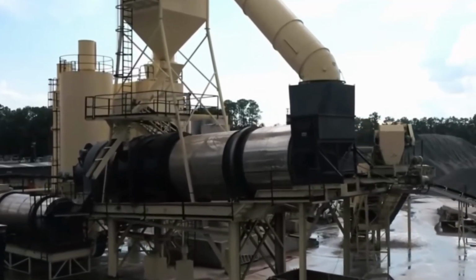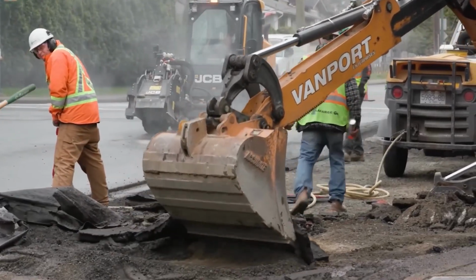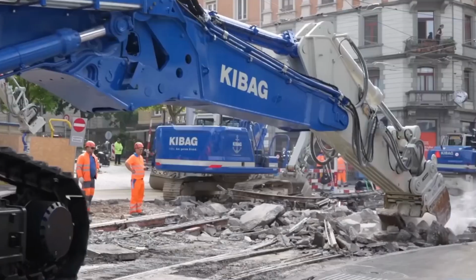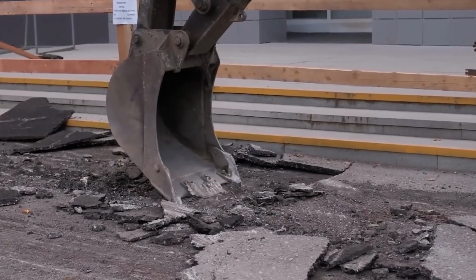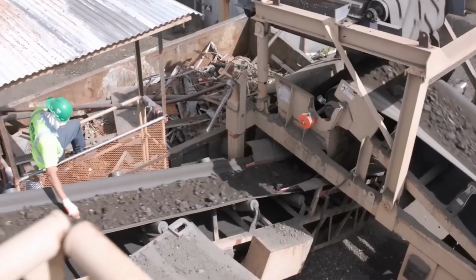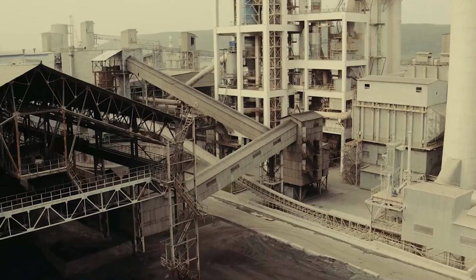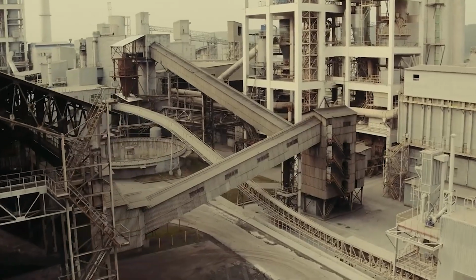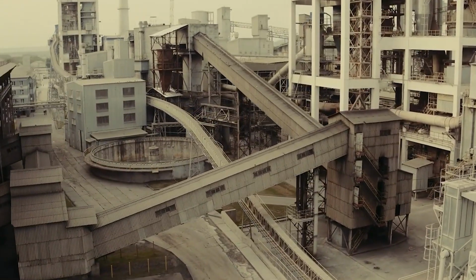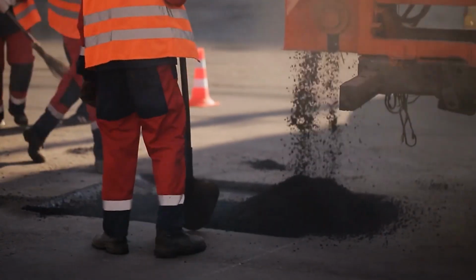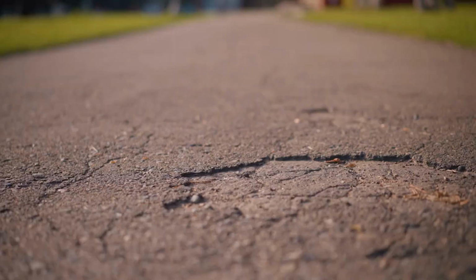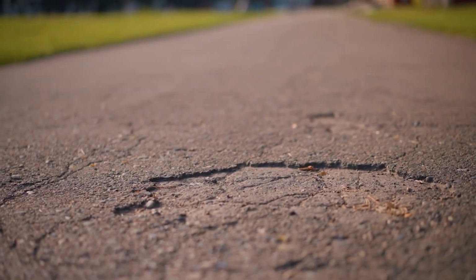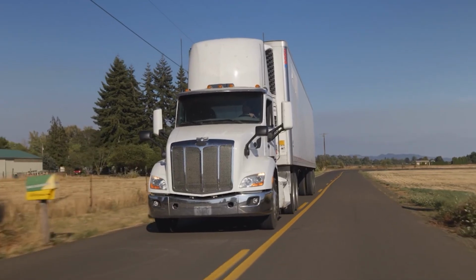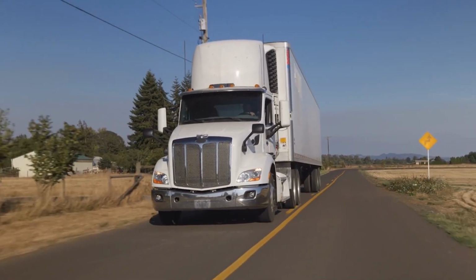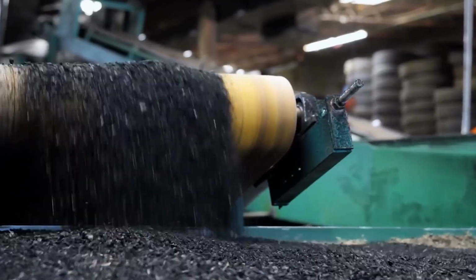Binder rheology, the chemistry. The stone is hot, the moisture is gone, but the old glue is still dead. The bitumen on these rocks has been baking in the sun for 20 years. Asphalt binder is composed of 4 fractions: saturates, aromatics, resins, and asphaltenes. Engineers use a blending chart to calculate the recipe. They determine the viscosity of the old binder, the viscosity of the new virgin binder, and the dosage of the rejuvenator. Too stiff. Underdosing results in thermal cracking in winter. Too soft. Overdosing leads to plastic deformation under heavy truckloads, known as rutting. The binder is chemically active again.